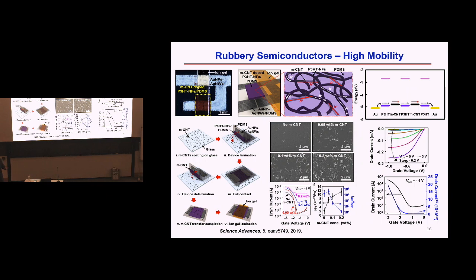Previously, our first generation material is using 2 material systems, double penetration network materials. The mobility is about 1. But here we really want to boost it. So how are we going to boost the mobility? Basically, we're introducing a third material. The third material approach is that we're actually incorporating metallic carbon nanotube on purpose to enhance the mobility almost by 10 times. This is our second generation of the semiconductor material.